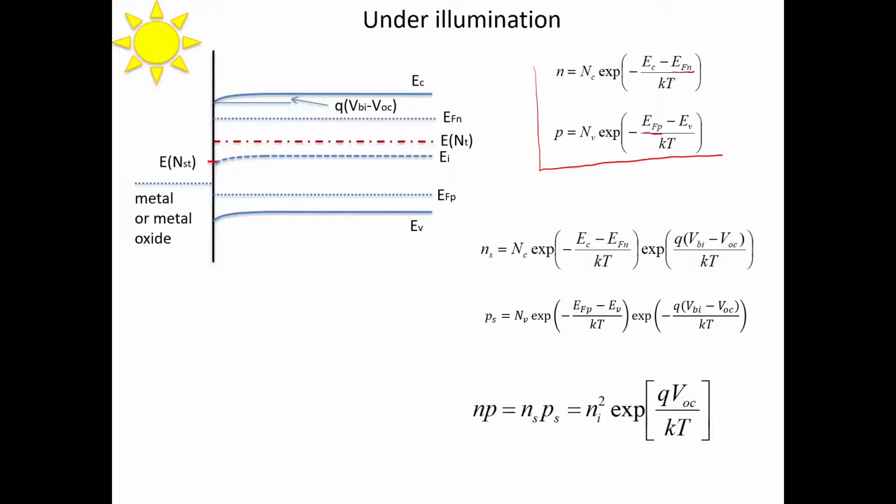So the same we can do for the surface, but we still need to take into account this residual band bending at the interface. So that's why we have concentration of minority charge carriers, like total concentration in the bulk times this exponent with argument where we have residual band bending divided by kT. For holes, at the total concentration of holes at the interface, we consider total concentration of holes in the bulk times this exponent with minus residual band bending divided by kT.